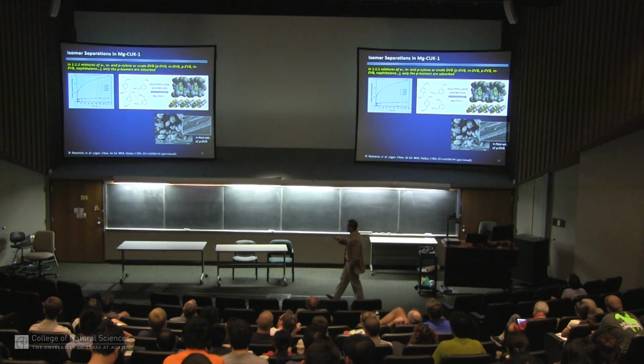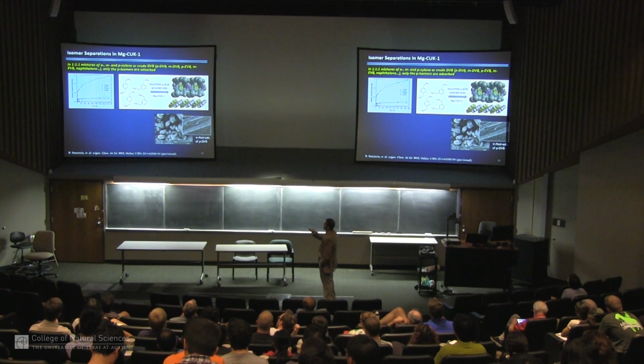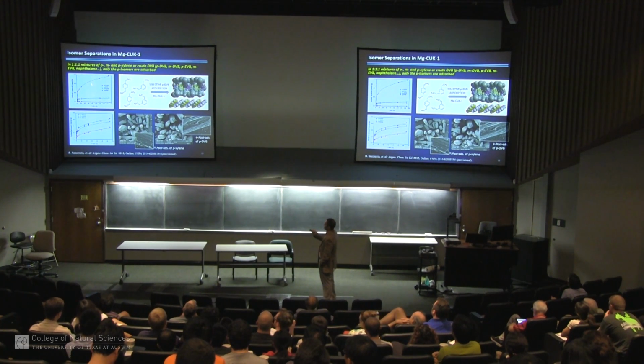The only limitation is, can you make the material fast enough and cheap enough to put it in a moving bed where you need tons and tons of the stuff. But this has a much better separation than the zeolite loaded with barium X, which is what they're using for this process at the moment. And so we've looked at the uptake characteristics of this material by kinetics. You can see the para isomers push everything else out of the material, and the same is true for the xylene as well as this divinyl benzene. This is used to make Dowex resin.